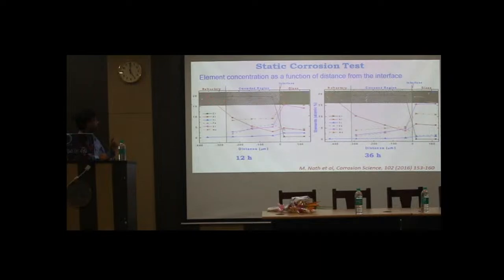You see the sample, one portion of the photograph, and this portion's atomic ratio is 1:1. So this is Cr2O3 and Al2O3, aluminium and chromium concentration is there, and a small amount of titanium is there. I think the blue one is the Ti. This is actually the metal concentration, and this is the glass side. So the chromium concentration is fixed, and chromium concentration is almost zero on the glass side. That means the chromium in this alumina chrome is not diffusing; chromium is not participating in the reaction. So what is happening? You see the aluminium concentration continuously decreases throughout the length of this corroded region, and the concentration is much less near the glass.